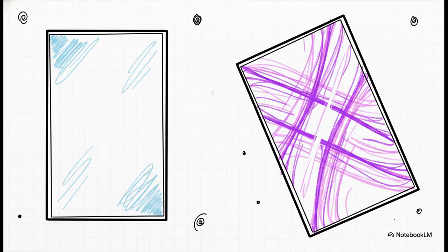Now, on the flip side, look at that perfectly flat optical window. It has an anti-reflection coating precisely engineered to work when you look straight at it, at a 0-degree angle. But watch what happens when you tilt it to 45 degrees. The angle at which light travels through the film changes the physical path length of the light wave. So to the light, the coating suddenly seems thinner. Because the apparent thickness changes, the interference changes, and the center wavelength shifts toward blue. This means the window suddenly starts reflecting vibrant violet and pink light instead of being totally transparent.